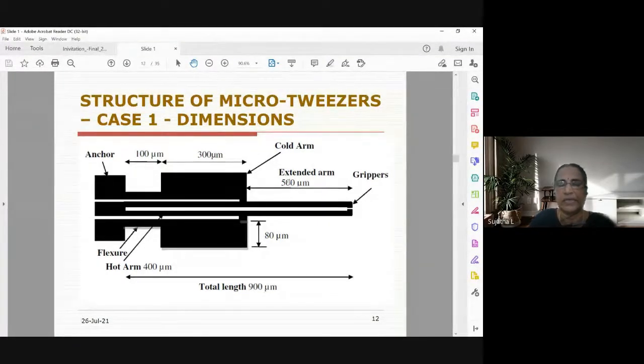But it is very difficult to increase the length of the extended arm because it will not be a rigid structure. It may get damaged very quickly after operating 1 or 2 times, or when you apply more force, this beam will break. So how can I increase the force without increasing the length of the extended arm? So how can I get the maximum force? That is the question. And you can see that the total device length is, this is 500, this is 300, and here 100. So totally 900 micron is the device length.